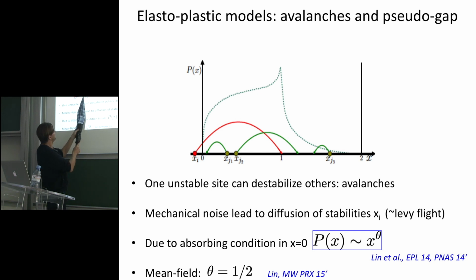When this happens, all the other sites are going to get a kick of stress, and therefore their parameter xi is going to change. The sign can vary, and some will get small kicks because they were very far away from the block i. Some will get large kicks because they were close to the block i. And so those kinds of models display avalanche type response, because if one guy becomes unstable, then in response, other guys can become unstable, which themselves can trigger other instabilities, and at the end, you can have big events where many sites actually relax.